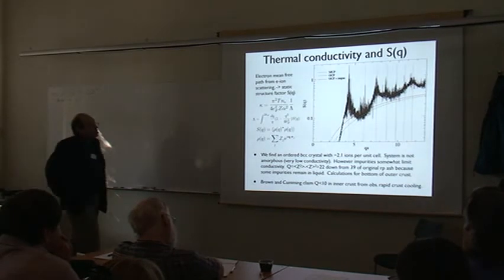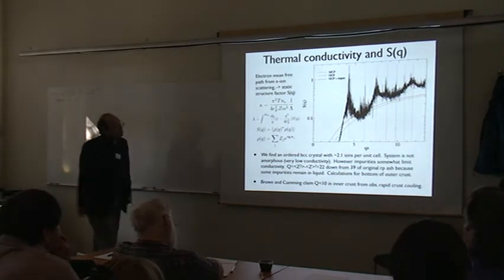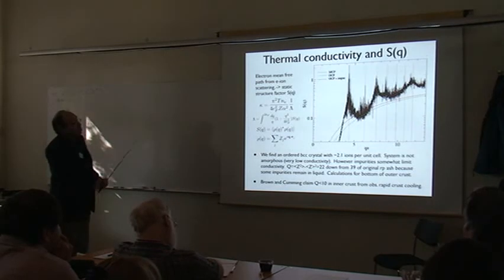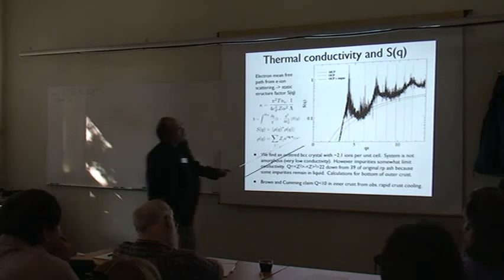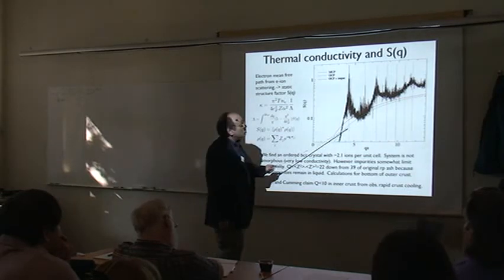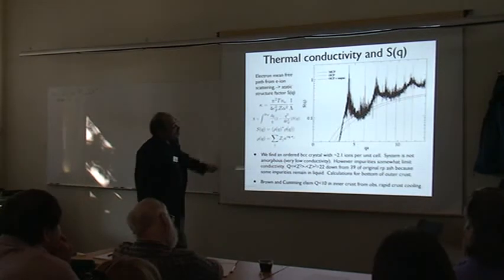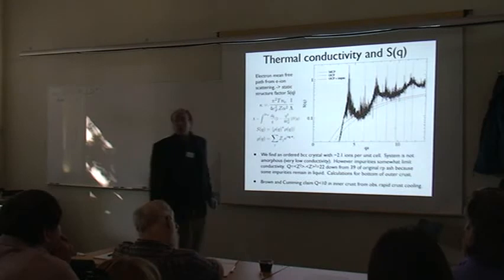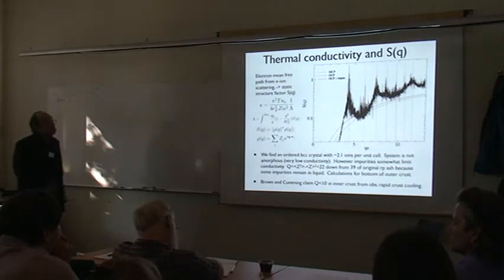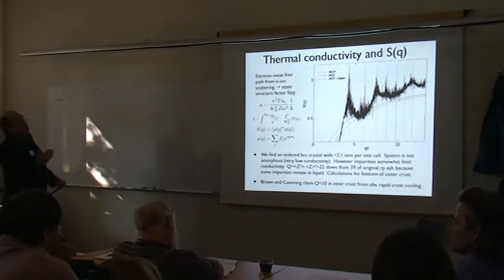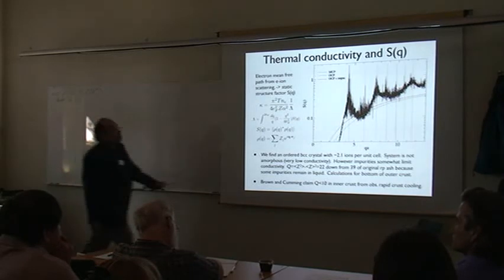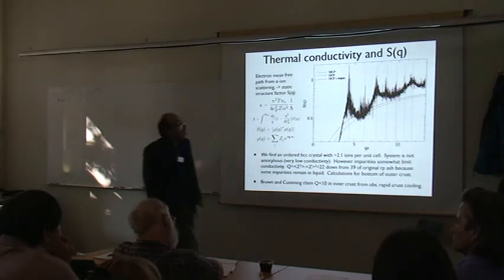If you had a pure system, no impurities, a one-component plasma, an ideal crystal lattice, at some temperature, you get the green static structure factor, with spikes at the Bragg peaks. You have a crystal lattice of particular momentum transfers, and the location of the Bragg peaks are these red dotted lines.